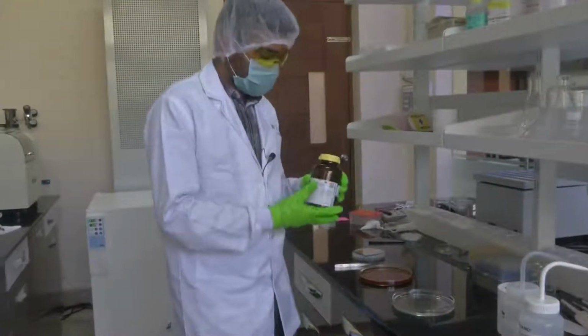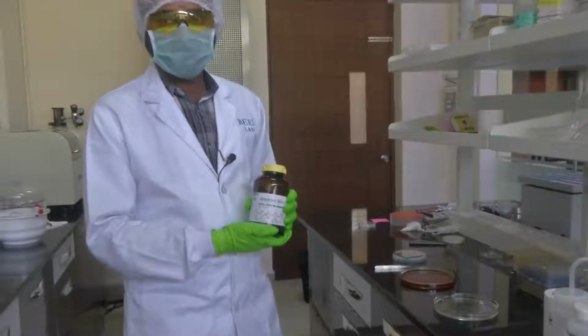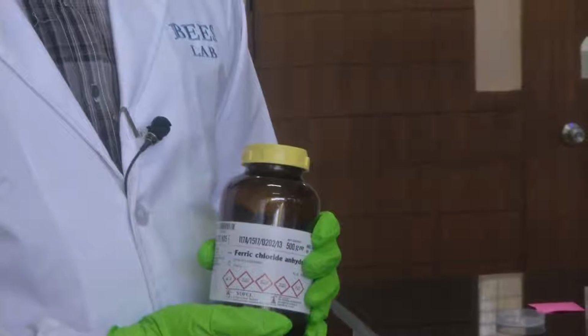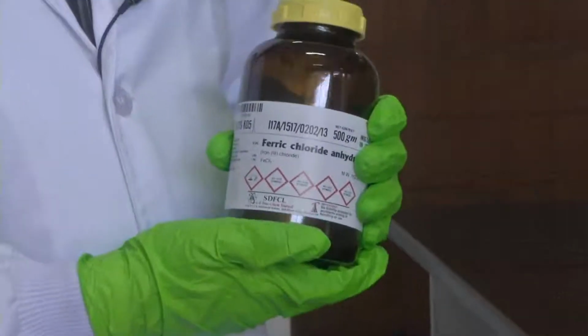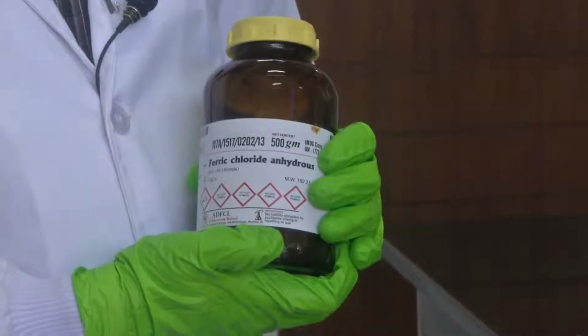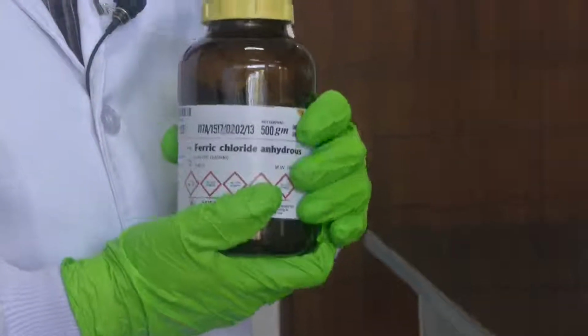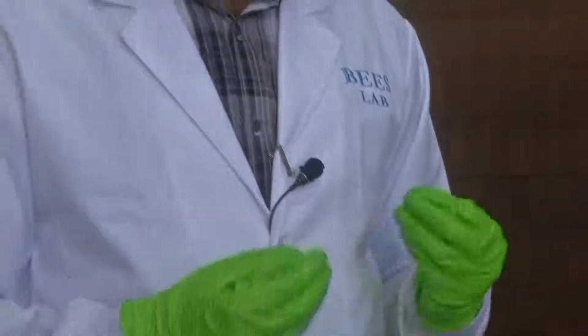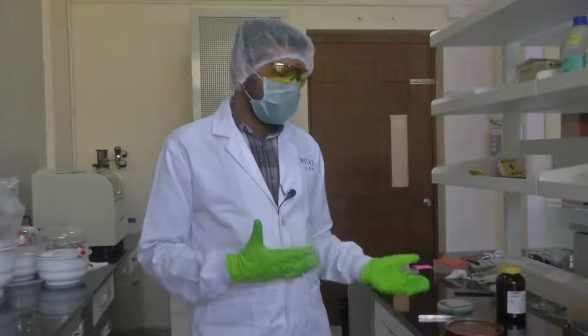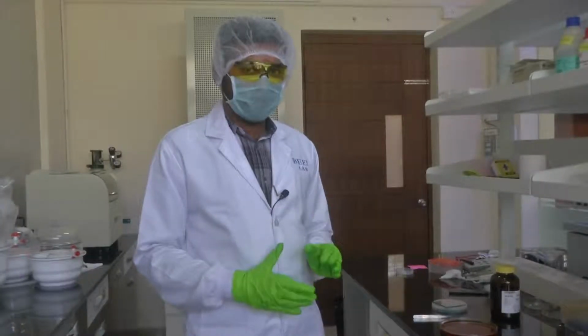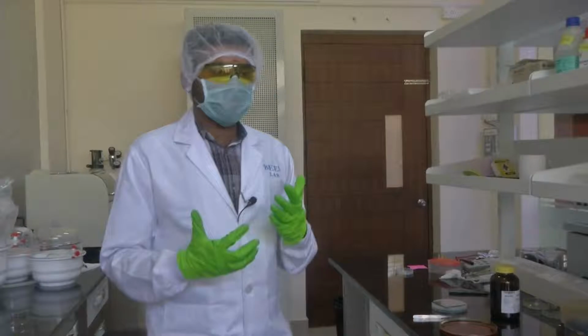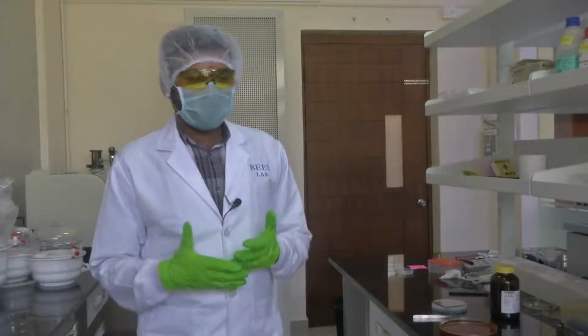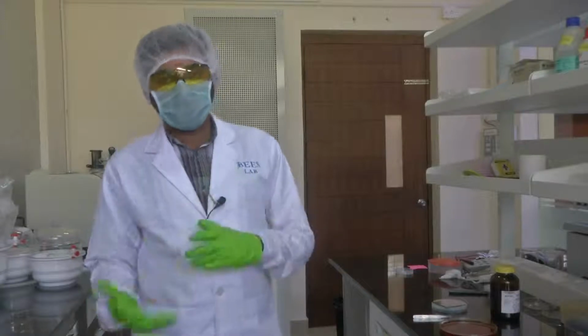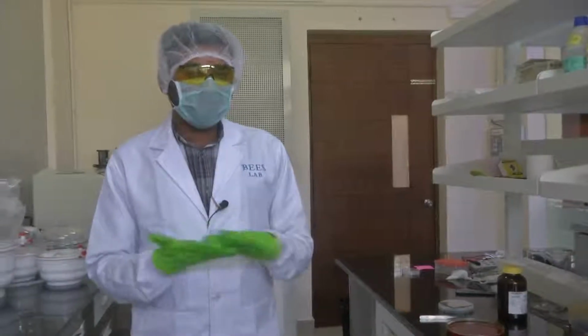So the etchant that we use for nickel etching is ferric chloride. So this is ferric chloride anhydrous, that means it is dry ferric chloride. So we take a specific amount depending upon the concentration that you need for the etchant, let us say 3 grams, 10 grams, and then dissolve it in 100 ml or 200 ml of deionized water. Okay. So for every process, let us say you have deposited your metal with sputtering as compared to depositing your metal with E-beam evaporation. The metal coating that you have on your glass slide will vary. Accordingly, your etch rate will also vary.